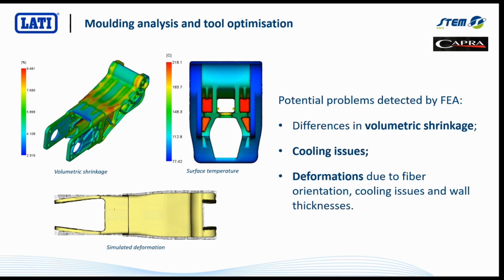So if you simulate the deformation that comes from a combination of those two effects above, plus the combination of any fiber orientation that we get during the molding as well, then what we were looking at is something like this, and this is clearly no good, because this is the end where we want to fasten into the carbon fiber legs.